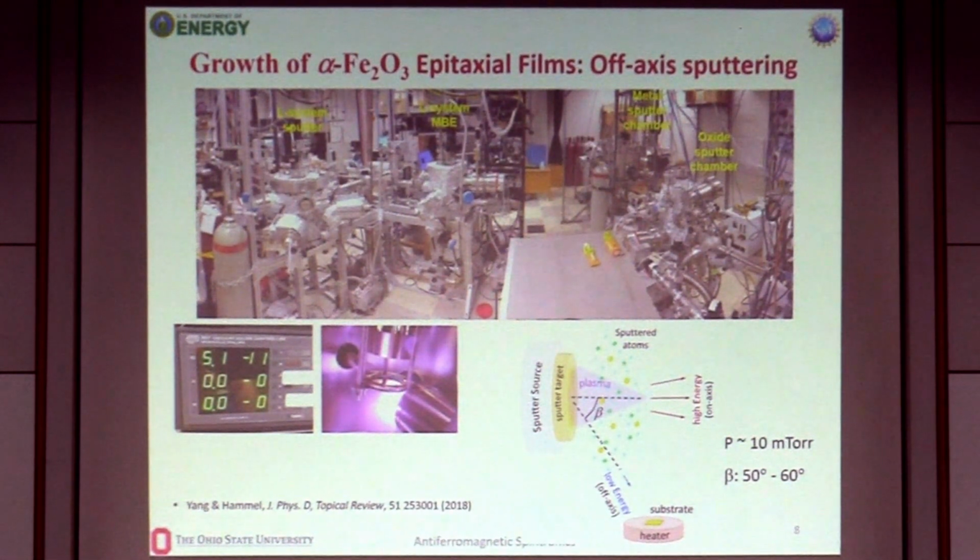And then, understandably, you're going to have pretty energetic atoms being ejected. There are some measurements of their energy. It could be from 10 to 10s of eV. But if you have oxygen in there, you're probably also going to experience some oxygen bombardment as well.